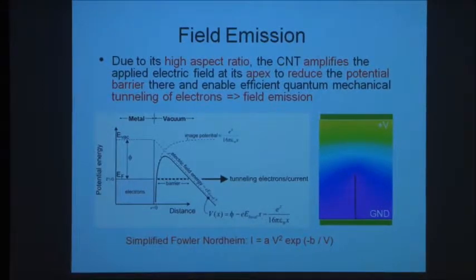But another way of doing it is, instead of using temperature to give them an increase in energy, you apply a high bias and get them to tunnel through the surface barrier. That's called field emission. By application of a high enough positive bias, you can drag electrons out through this barrier. It's a bit difficult with a flat surface: you put a high bias here, the field lines just go like this, and you really need a very high field to drag electrons out of a typically flat surface. It's possible, but it does require very high fields.